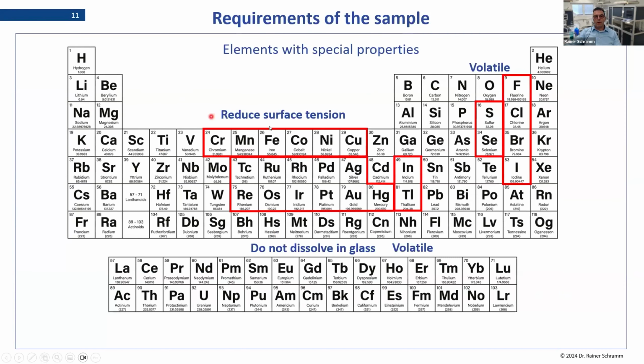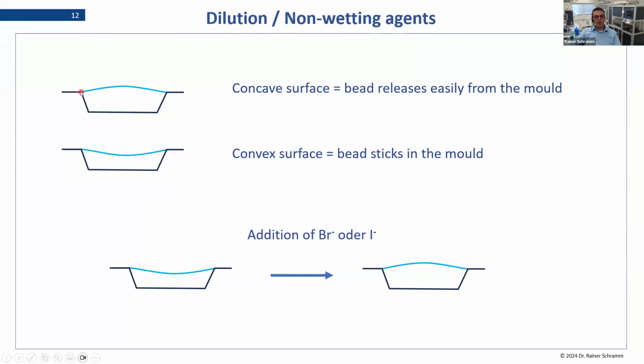Okay, but now let's talk about these elements which change the surface, so the ones which reduce the surface tension. For example, if a cement sample forms a bead with a concave surface, this releases much easier from the mold. These reducing elements make a convex surface, and then automatically these kinds of beads start to stick in the mold. The only possibility you have to change this behavior is to add bromide or iodide, so that in this way the surface tension comes back and it helps you to release easier from the mold.